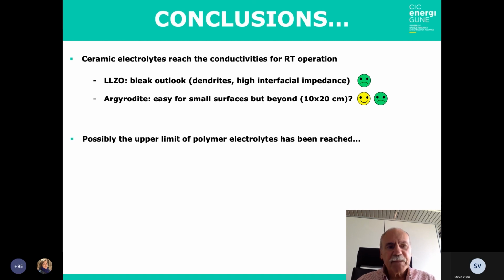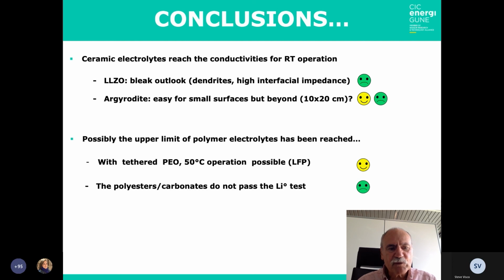Possibly, we have reached the upper limit of polymer electrolyte in terms of conductivity with a strategy I showed of tethering the PO segment to a tether itself attached to the backbone to increase the kinetics. With this tethered PO, a 50 degrees operation is possible without any problem. As I said, it can possibly go to 25. The polyester and polycarbonate, for which I did not show any slide because of shortness of time, do not pass the lithium compatibility test. So this would possibly be solved with a dual electrolyte, having a layer of PO on the lithium side, and the polycarbonate on the positive electrode side.